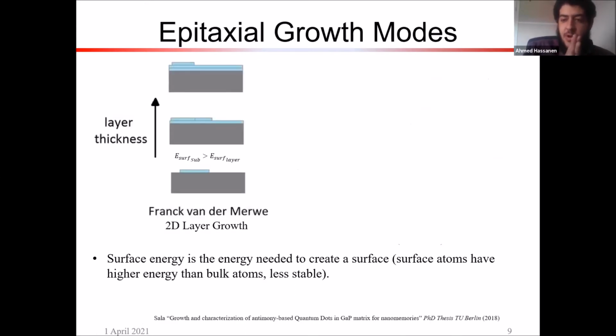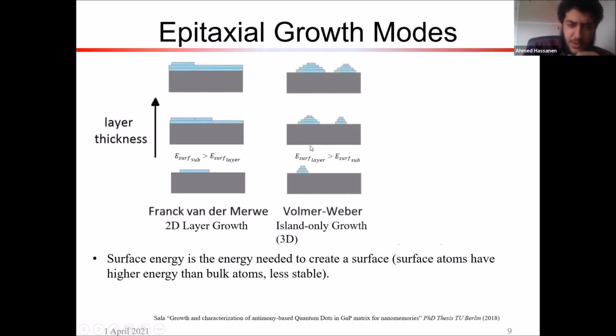And so, okay, now we want to know how to grow these quantum dots. And so just for epitaxial growth in general, we have several epitaxial growth modes. So for example, we have the 2D layer growth mode. And so depending on the surface energy considerations between the substrate and the layer we're growing, we can get different growth modes. And so we have this 2D layer growth mode where the surface energy of the substrate is higher than the layer. The growth proceeds in this 2D fashion. And when the opposite is true, we start to get these 3D islands.